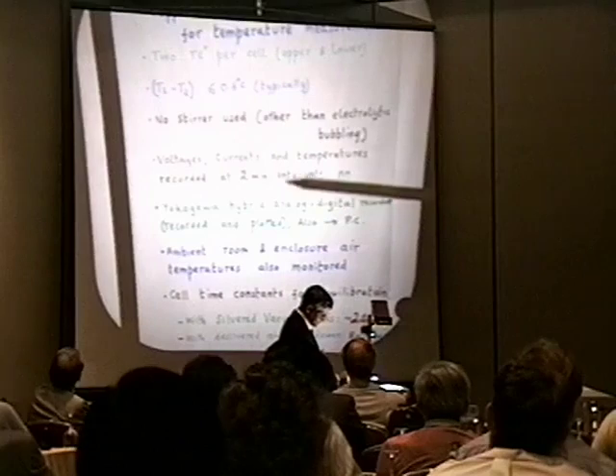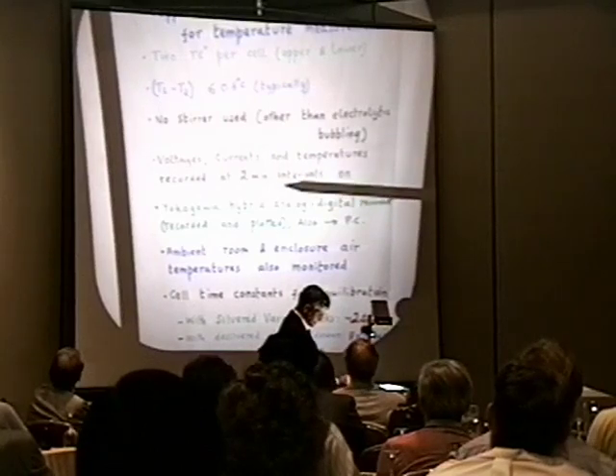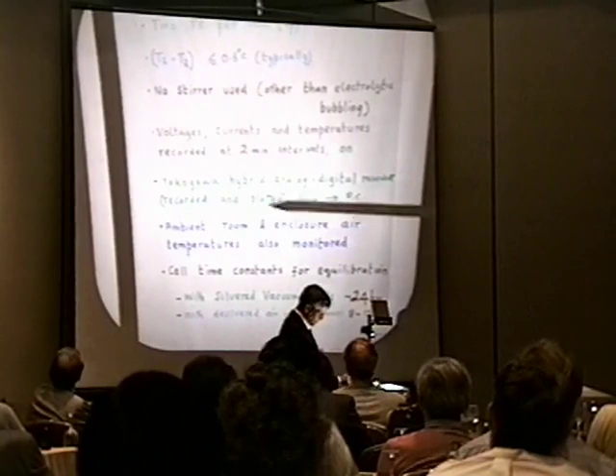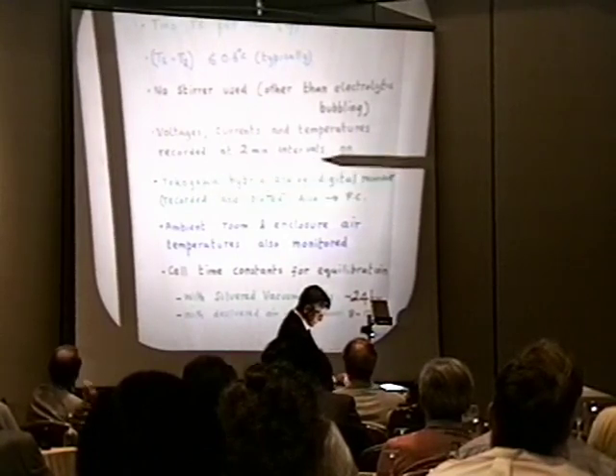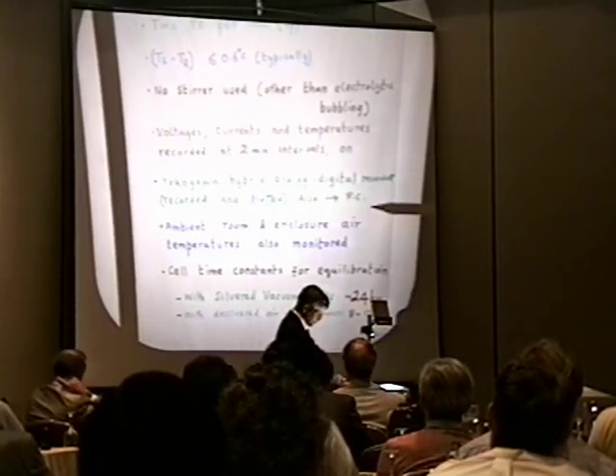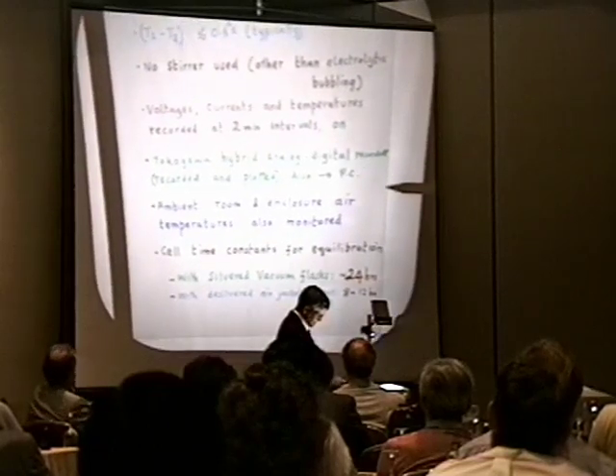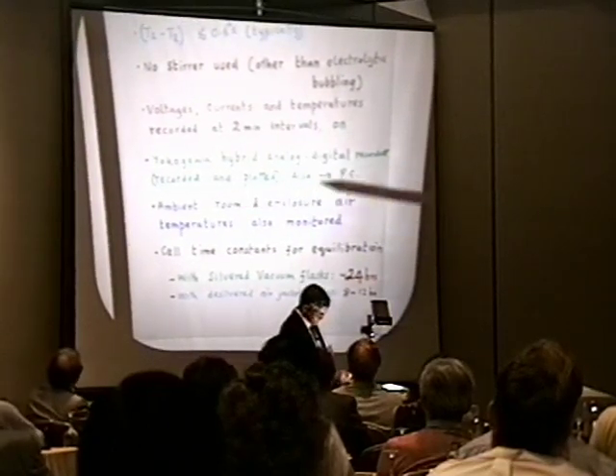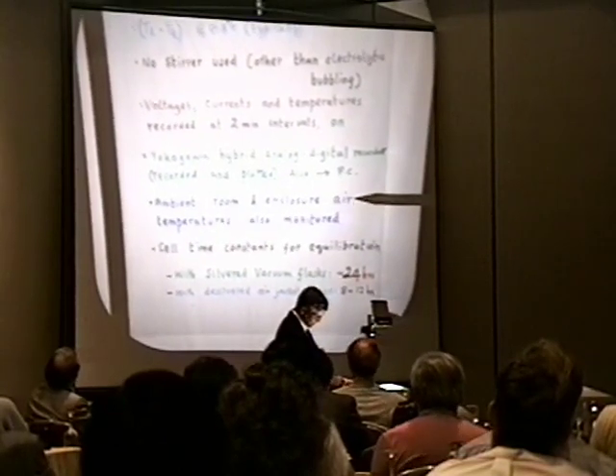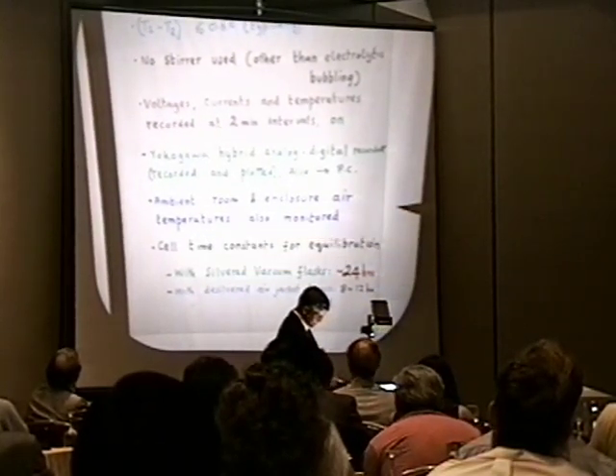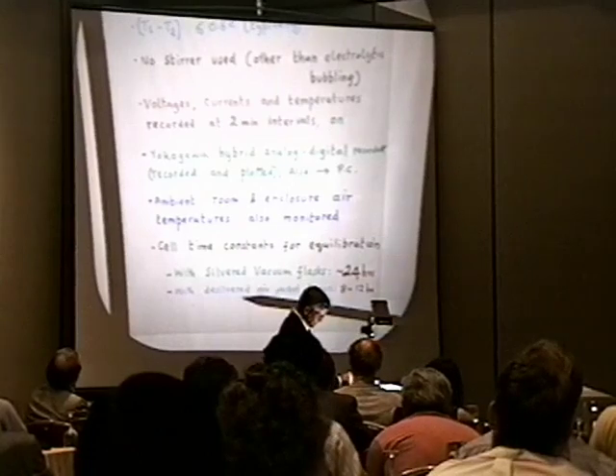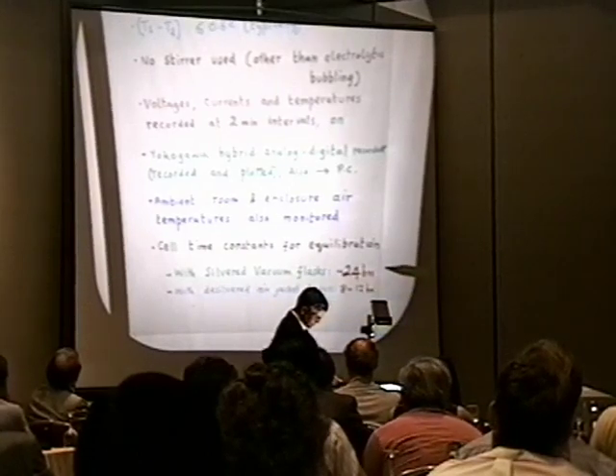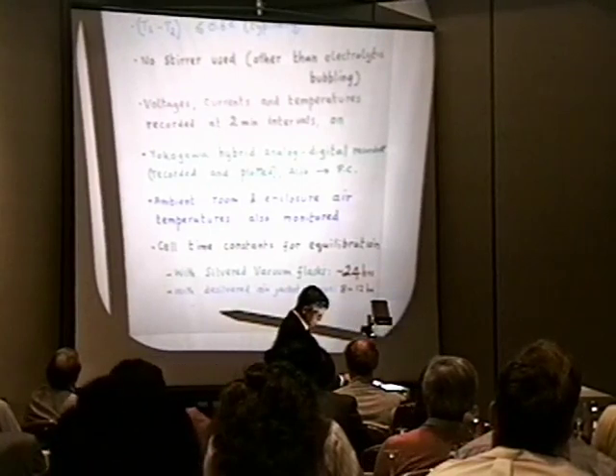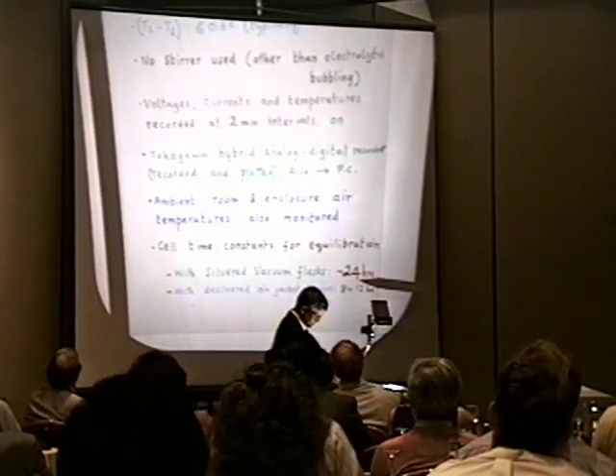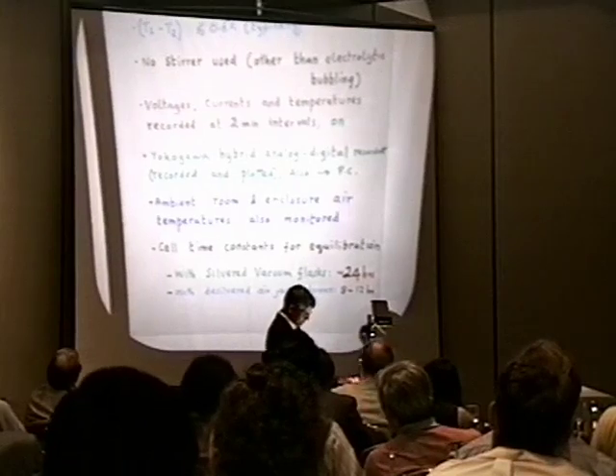And voltages, currents and temperatures were continuously recorded at 2-minute intervals using what we call a Yokogawa hybrid analog digital system, which is hooked up to a standard personal computer. The ambient room and enclosure air temperatures are also monitored and recorded. Typically the cell time constants for attaining equilibration with the silvered vacuum dewar flask was typically 24 hours, and with the desilvered flask, because of the lower sensitivity, it was equilibrating within 8 to 12 hours, depending upon the power put in.